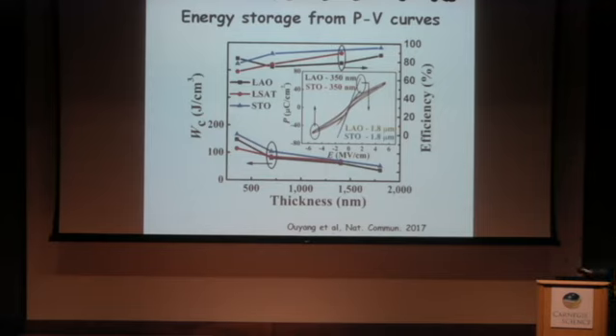Here, just quickly show you the experimental results. So these loops are for the thin film. You can see very slim, but still you can see some loss there. And this film has an efficiency of 85 to 90. But when you grow really thick, you almost think you're looking at a linear dielectric.